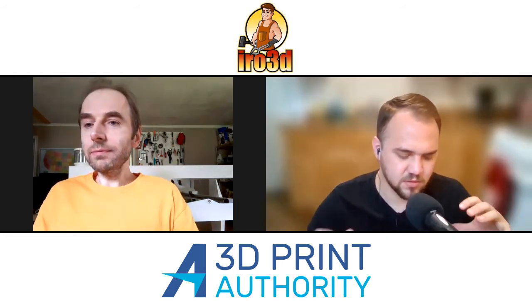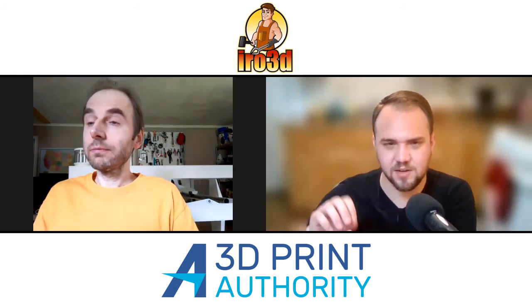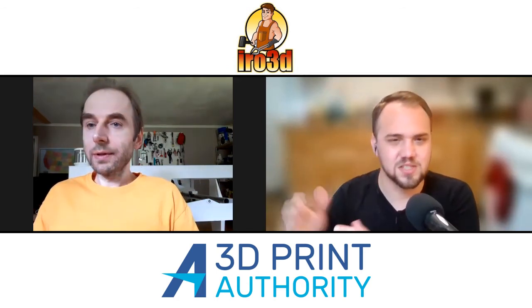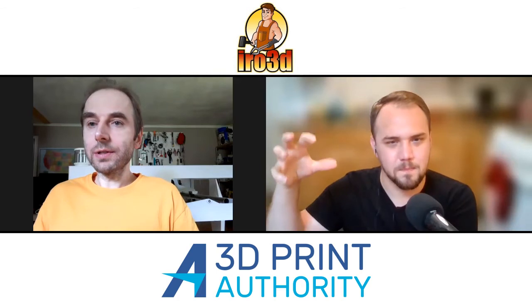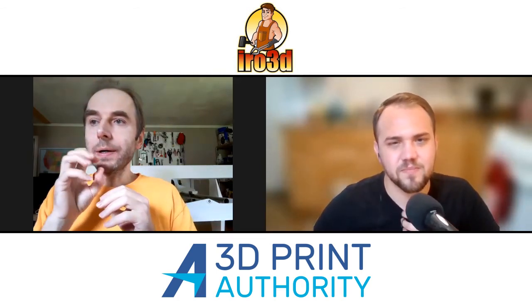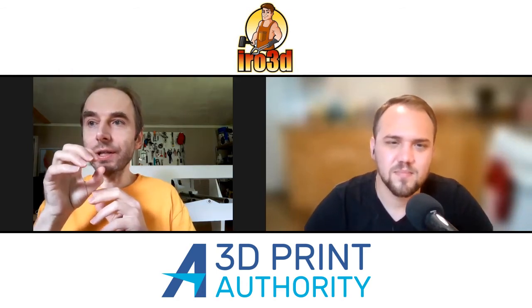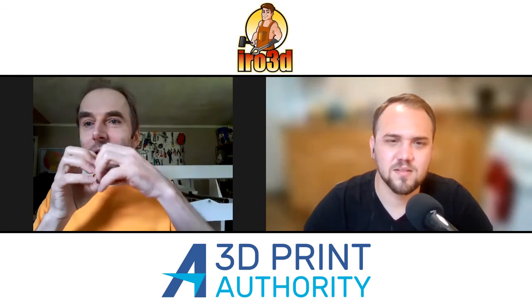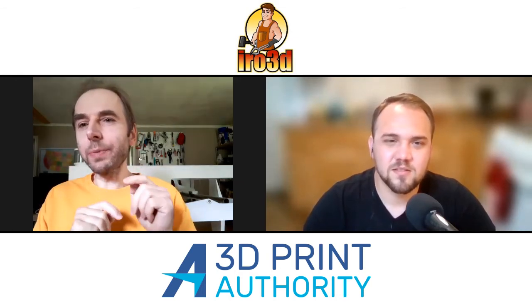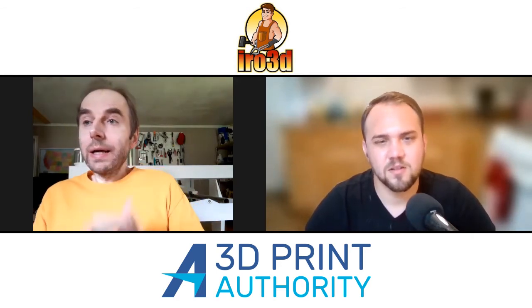So in laser sintering systems, from what you're saying, it creates a lot of stress within the part because it's kind of sintering at a pinpoint, and that's different in your process because it's melting all at once. Yes. So when they melt and it solidifies, it cools down, and it shrinks, so it pulls the other parts next to it. So you end up with lots of microscopic cracks. So it's not just bad for the warping.